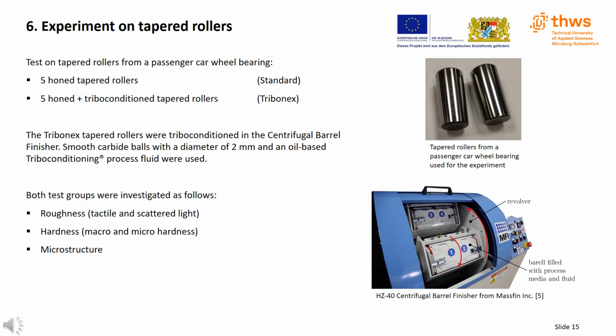In both test groups, the roughness was measured tactilely and with scattered light. In addition, macro and micro hardness were checked. A possible difference between the micro hardnesses could indicate an increase in residual compressive stresses due to triboconditioning. Finally, the microstructure was examined under an incident light microscope to detect potential grain refinement.